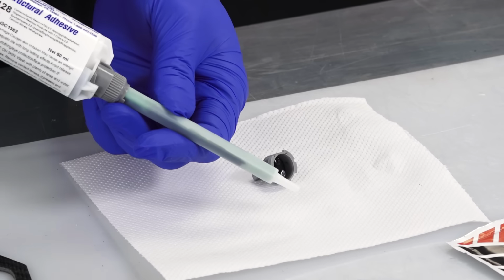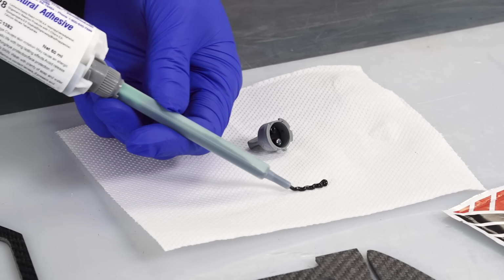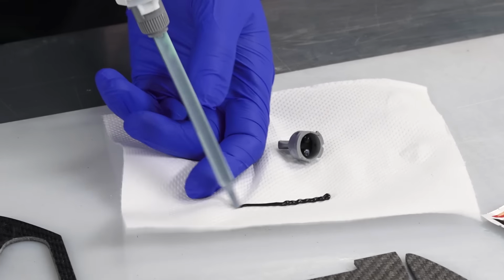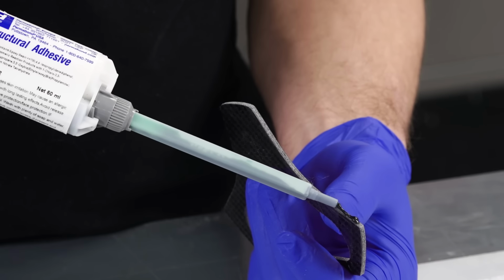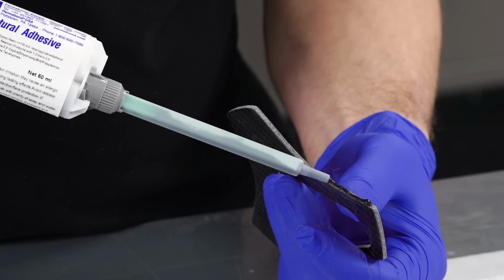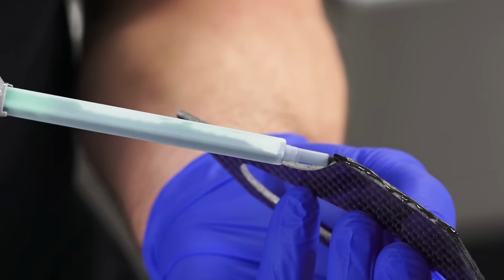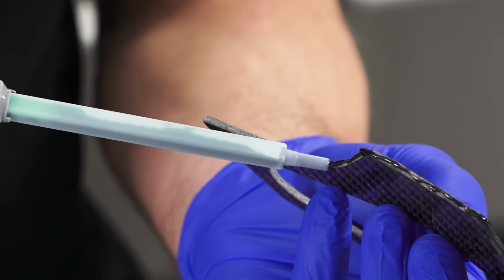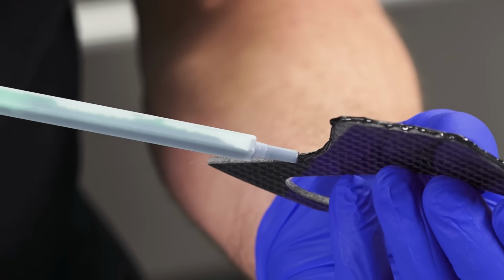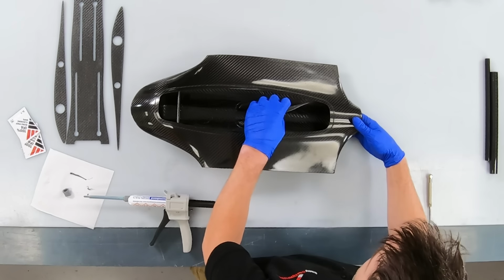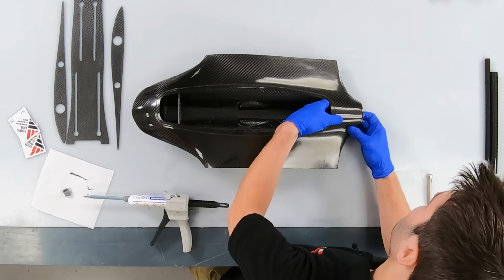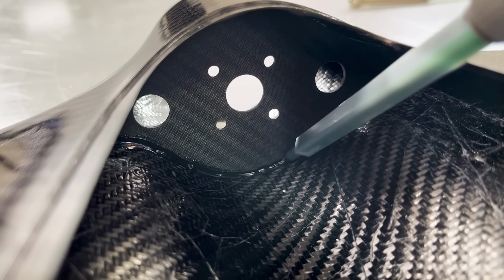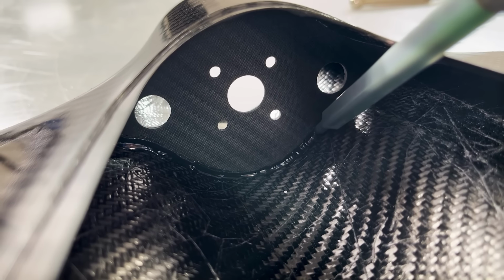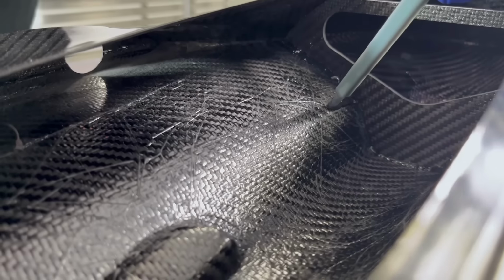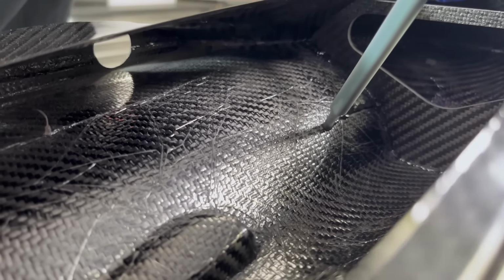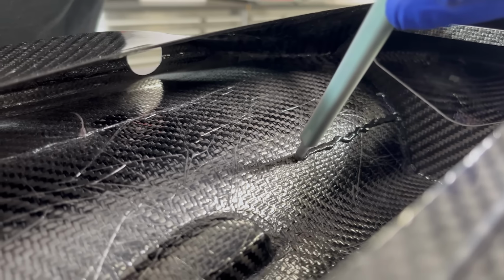I like to sacrifice a small amount of the adhesive at the start, as there's always a bit of a chance that it's not perfectly mixed. It's then applied in a thin bead along each of the bonding faces. ET5428 has a working time of around 10 minutes, which is more than enough for this job, but as I mentioned earlier, we do have the 2.9 version that will give you over 2 hours if you have a complex assembly to bond.